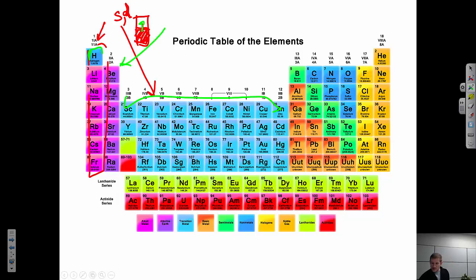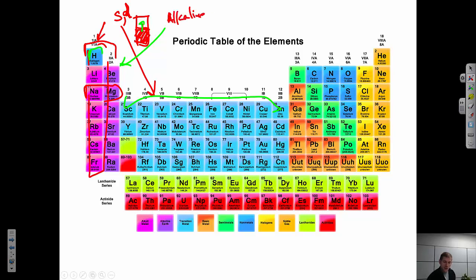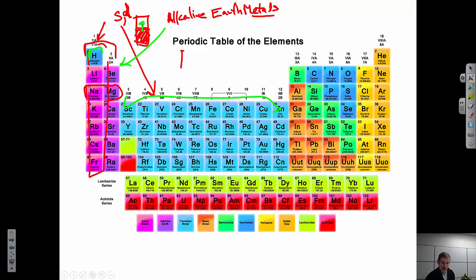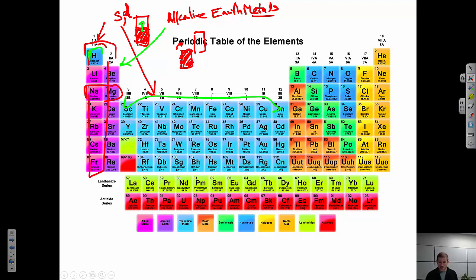The alkaline earths are a little bit different because I would have a full s orbital. For example, magnesium would have a full 3s orbital, but we think of these as metals — we call them the alkaline earth metals. They do behave metallically, but it's a slightly different picture. In this case, the 3s orbital and the p or d orbitals end up overlapping. So even though I have a full s orbital, there are still available energy levels at slightly higher energy for these electrons to be excited to. This is kind of like that semi-metal picture.